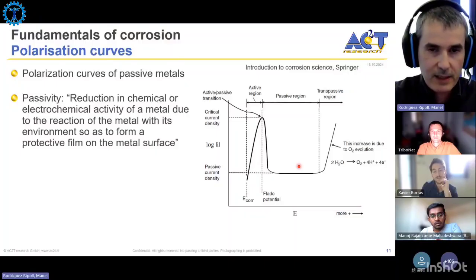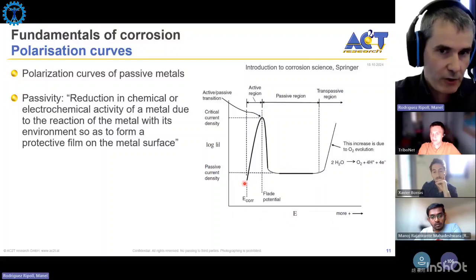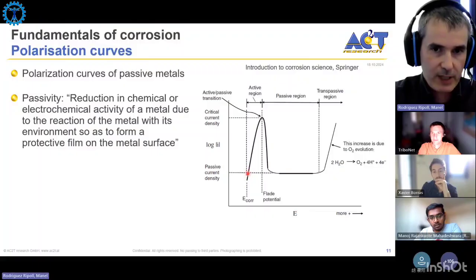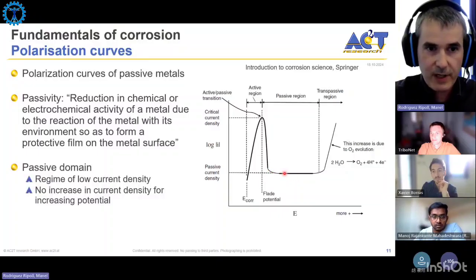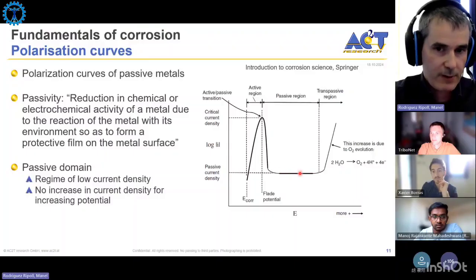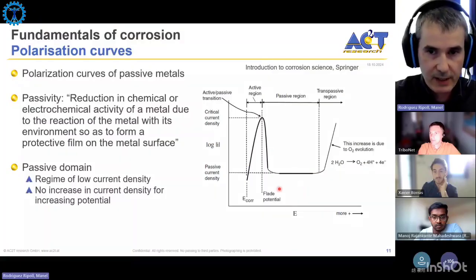And in this case, on this anodic branch of the polarization curve, when we apply a potential, it may occur, not always, that at the beginning we have an increase in the current density. So it means that we are corroding the material more when we apply a voltage, but all of a sudden we have what is called the active-passive transition, and at some point the current becomes very, very low. So we have a region with a very low current density. It means that the corrosion is very, very, very slow. And also the current density is independent of the applied potential. So we can increase the potential, but the current density remains the same.